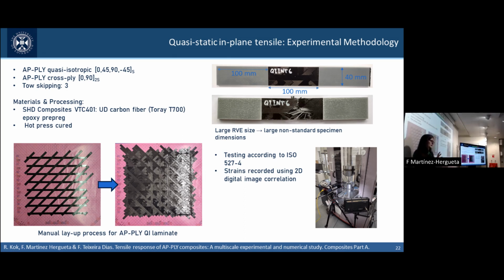relatively large representative volume elements, and we need to consider them when creating our coupons. So we might need to adapt the current standards that we are using in order to be sure that at least one representative volume element is contained. That means that our samples are slightly bigger than the conventional ones, with 40 millimeters width.